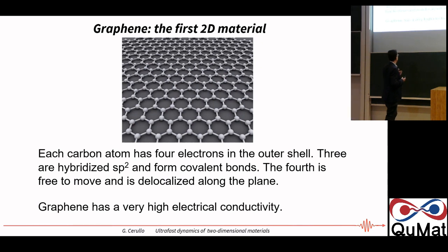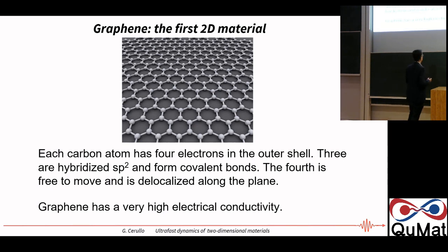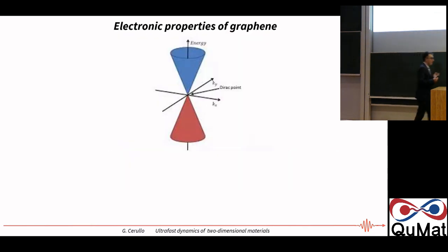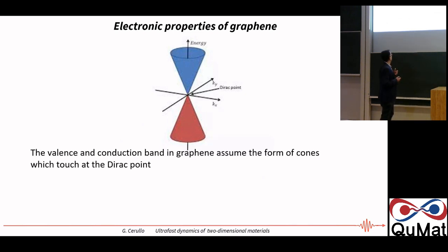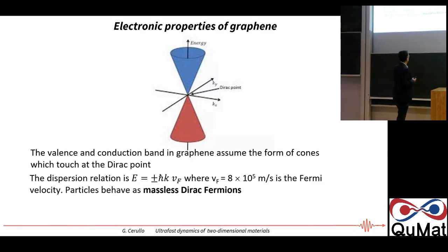Now, in graphene each carbon atom has 4 electrons in the outer shell. 3 are sp2 hybridized and form covalent bonds, and the 4th is delocalized along the plane, so that graphene is a semi-metal with a very high conductivity. But graphene also has a remarkable band structure. The bands in graphene are the famous Dirac cones, which touch at the Dirac point. And essentially, if you take the derivative of energy with respect to momentum, you get a linear dispersion relationship, and the charges behave like so-called massless Dirac fermions.